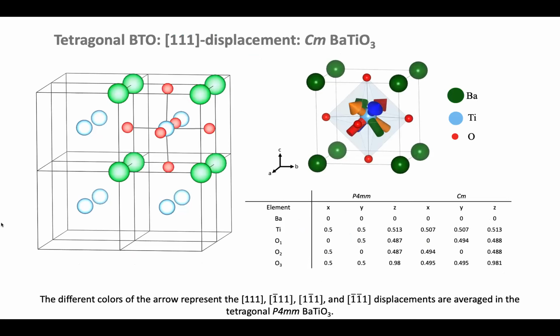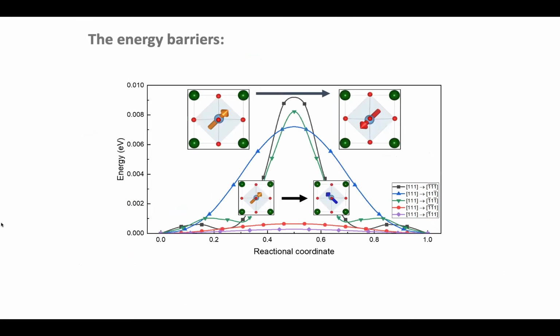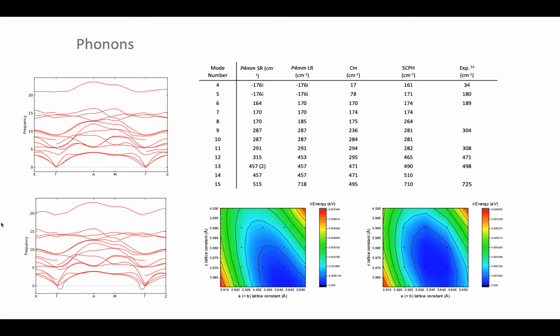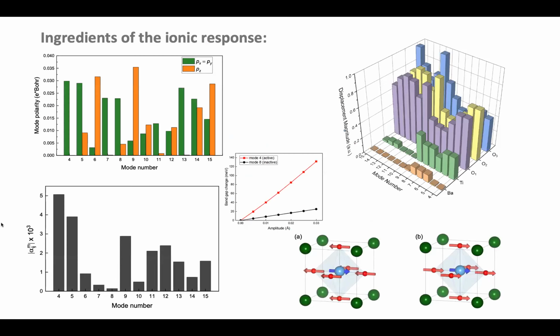So if you try to do the P4mm, nothing works. Not only is it dynamically unstable, but nothing works, right? And so we looked in the literature, argued with the reviewers, and came to the conclusion that the reasonable structure you need to deal with is actually Cm, where you displace atoms along 1, 1, 1. And then you take like 8 of them, and you can always make it into P4mm. If you do that, then everything works more or less well. I'll skip that. So everything works, and you get the active and inactive modes.